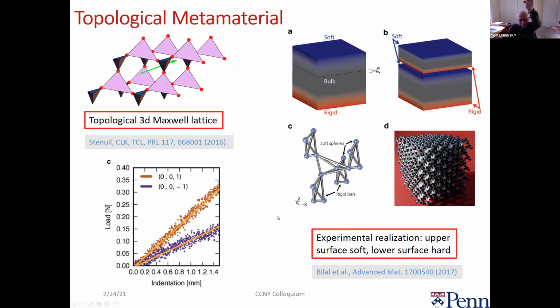So when you stick a pole into one side, it'll cause the surface to invaginate, and you can measure how deeply it goes. And you can look at the difference. So what load does it take for a given indentation? On the bottom surface, this reddish orange thing, you have the load versus indentation grows like this, whereas the load versus indentation for the top surface is much lower. So this says that I really do have a polarization between the top and bottom surface. They have different mechanical properties.